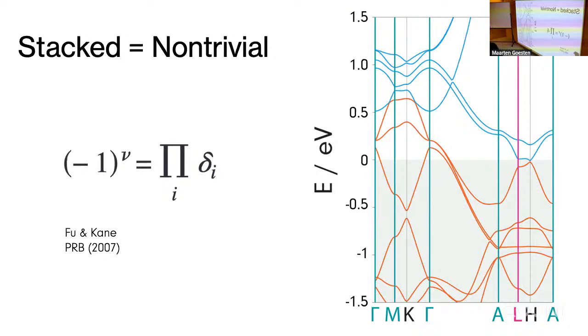Essentially, only at the points in the Brillouin zone in reciprocal space where the wave vector is mapped onto itself by the inversion operation, which are called time reversal invariant momenta, so those are only points gamma, M, A, and L in our case, only in those points can we obtain a parity eigenvalue for the bands. If you have an odd number of occupied parity eigenvalues, you get a negative delta. You factorize that out, and if you then get -1, you have a strong topological insulator. In our case, this is invariantly a strong topological insulator, but pretty much also due to the interaction with this special band here that I will finish the talk with.